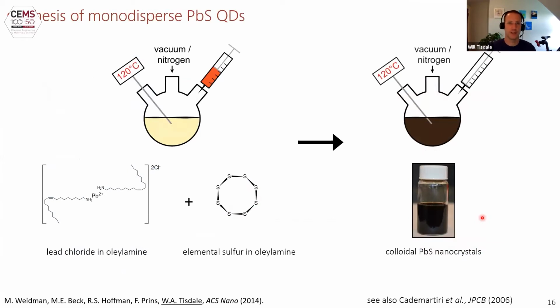In my lab, we synthesize our lead sulfide quantum dots according to a method originally developed by Cademartiri. It's a reaction of lead chloride and oleylamine with elemental sulfur under vacuum or nitrogen at modest temperatures. And if the reaction is successful, you get this very ugly coffee-looking thing. That's because these are near infrared band gap materials, so they absorb all visible light. So not as pretty to look at as the cadmium selenide materials, but very useful.